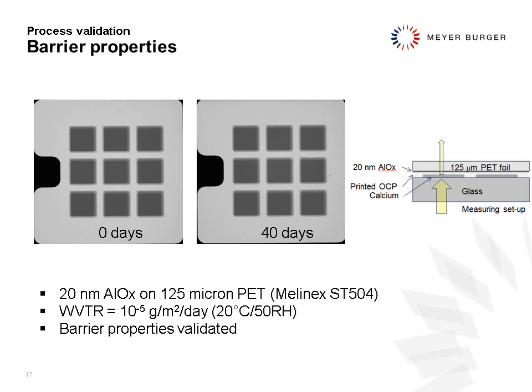Now, we deposit this. We talked about the 20 nanometer. Does it work? Well, if we deposit 20 nanometer on 125 micron of PET foil, you will get a WVTR in the region of 10^-5 at 20/50. So the barrier properties are validated.